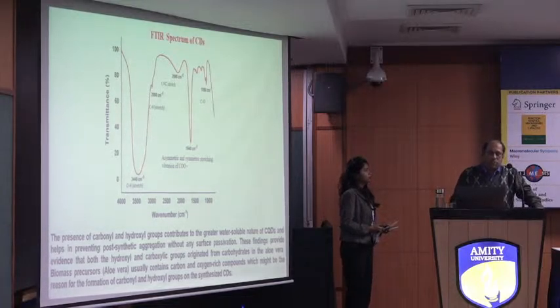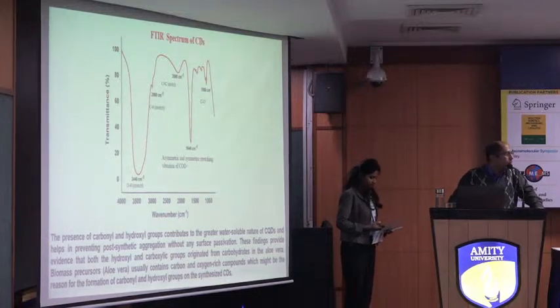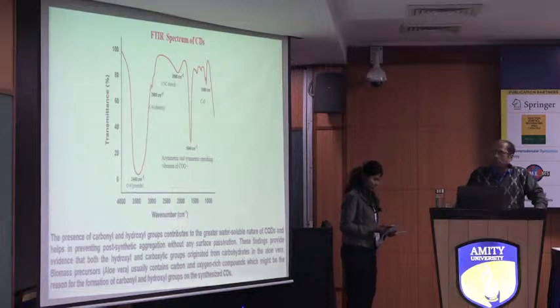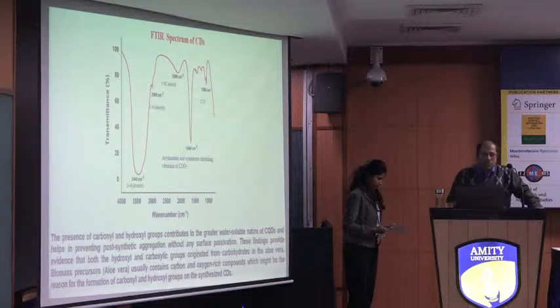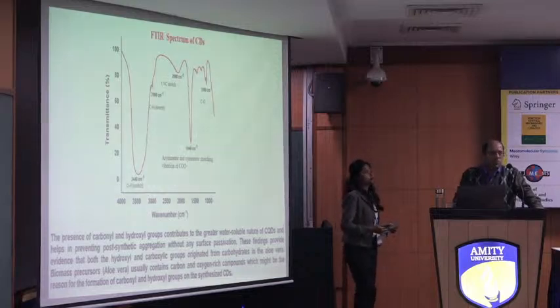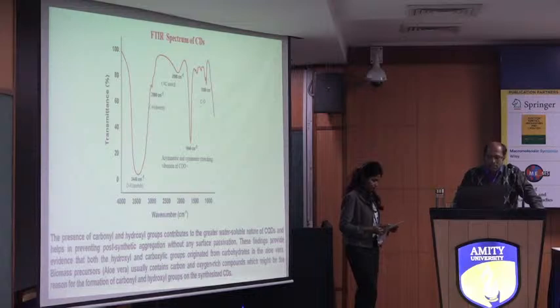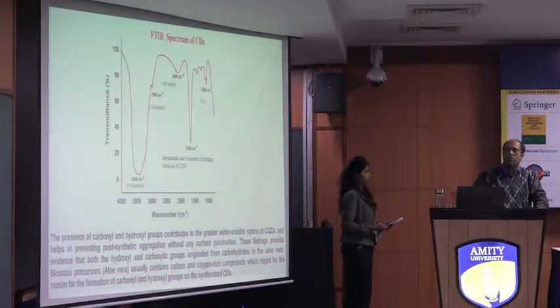To check the functional groups present on the surface of the carbon nanodots, we also performed the FTIR spectrum, which showed the presence of different functional groups like carbonyl or hydroxyl groups, C-C bond, C-O bond, etc. The presence of these carbonyl and hydroxyl groups contributes to the greater water solubility of these carbon nanodots, which helps in preventing post-synthetic aggregation without any surface passivation. These findings provide evidence that all these groups have been generated by the carbohydrates or other molecules present in the aloe vera.